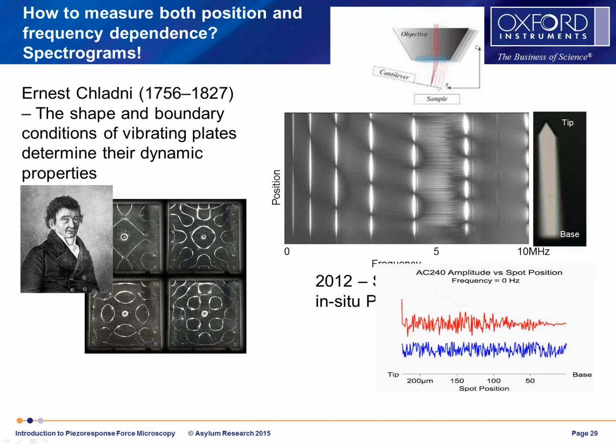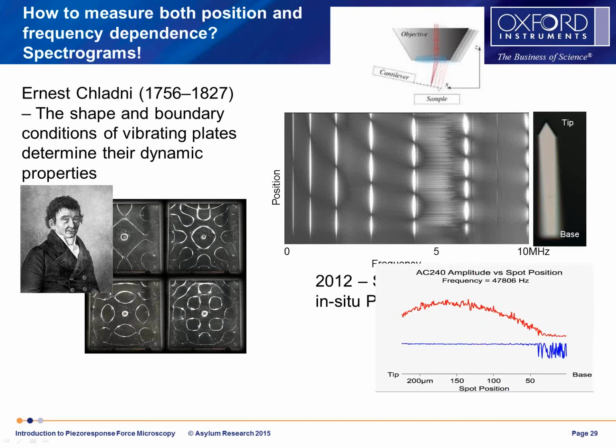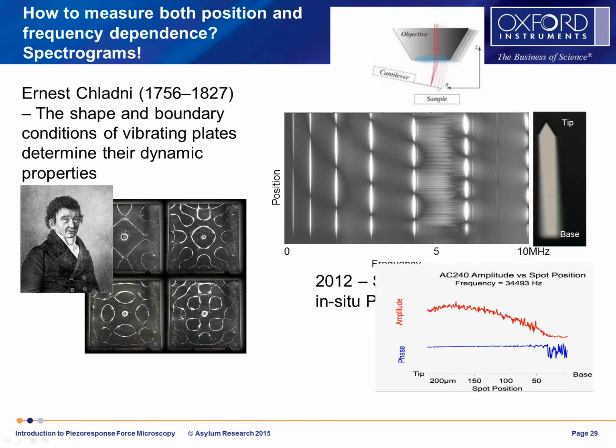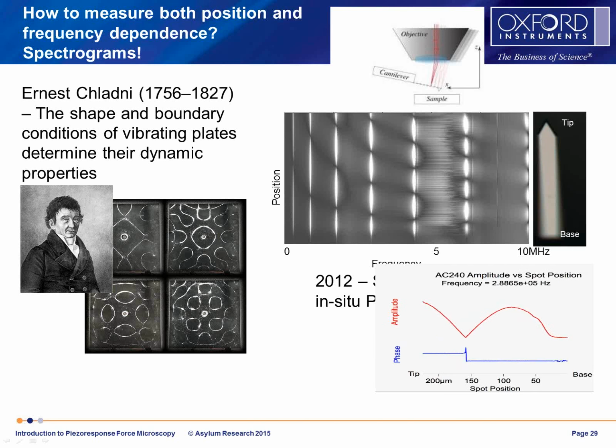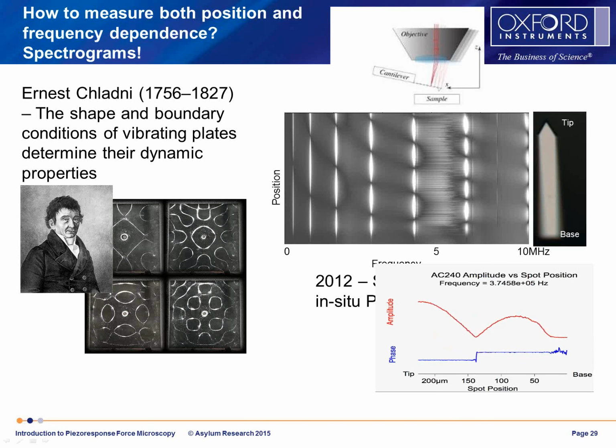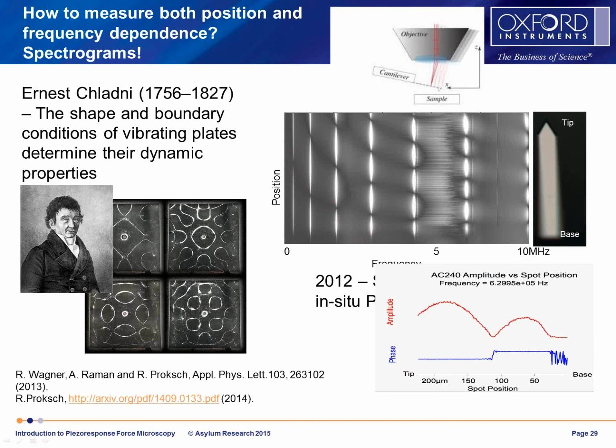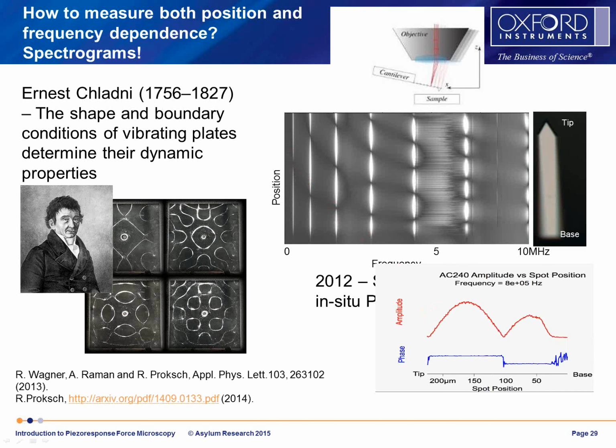This movie here, I can play it in a second, is that same data in the graphic up above, but now what I've done is I've shown it in cross-section so you can actually see the cantilever shape. Well, the amplitude shape anyway. We just went through the first resonance there. You can see this antinode that's actually visible right there. That's that node right there. As a function of frequency, we're scanning through the frequency here, and you can see this amplitude changes both as a function of position along the length and of the drive frequency.